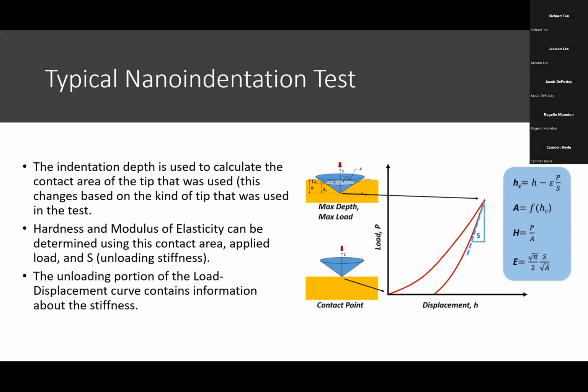If we look here to the right on this image, we can see there's a cone tip that is applied. It's left a maximum height from the surface to the max depth of the indentation. There's also a contact height from the max depth to where the tip no longer has contact with the material. And that contact height is in relation with the max height minus epsilon times the load force, divided by unloading stiffness.